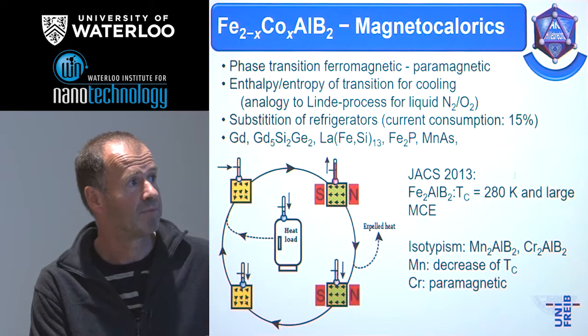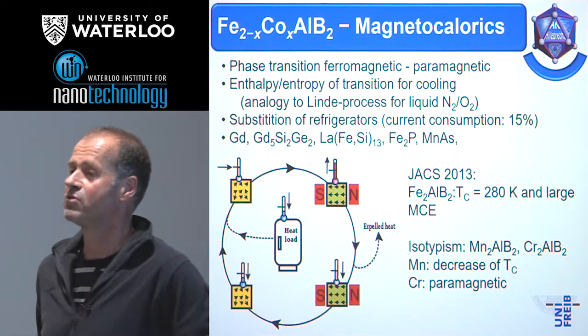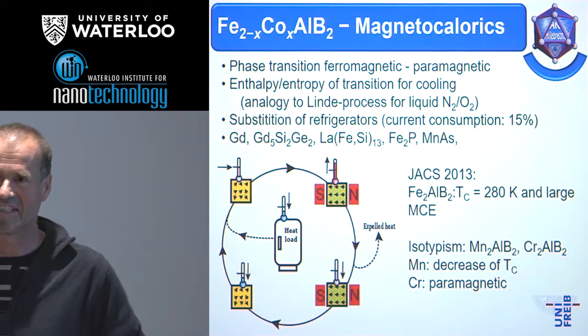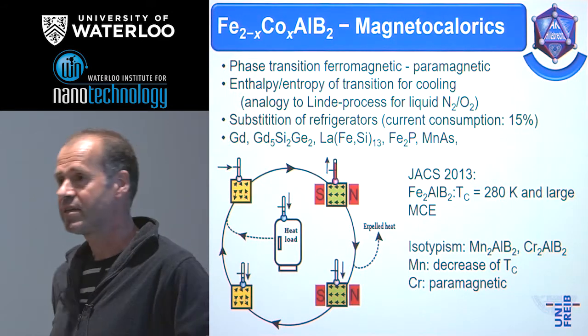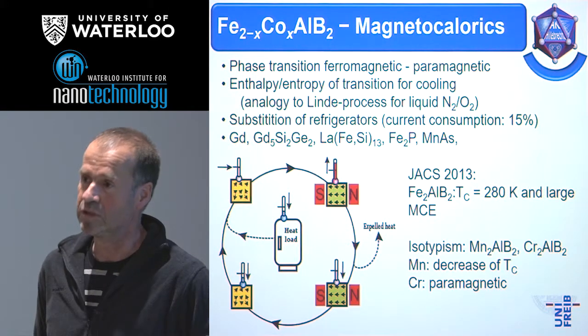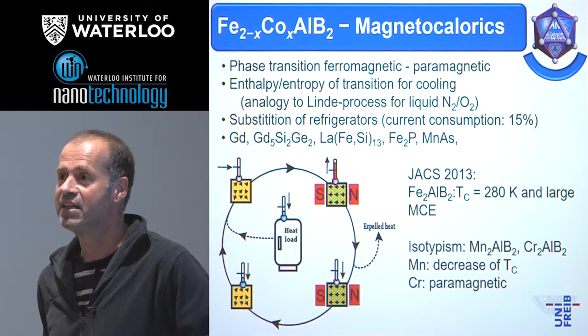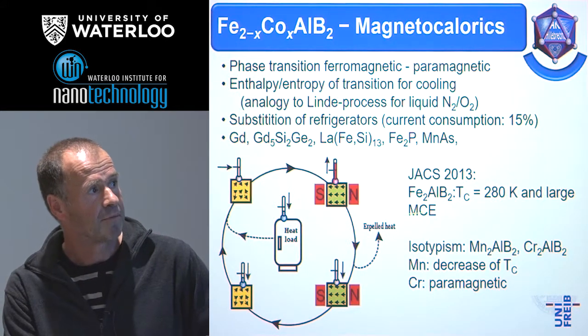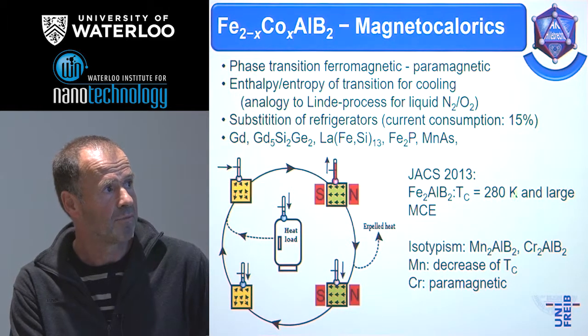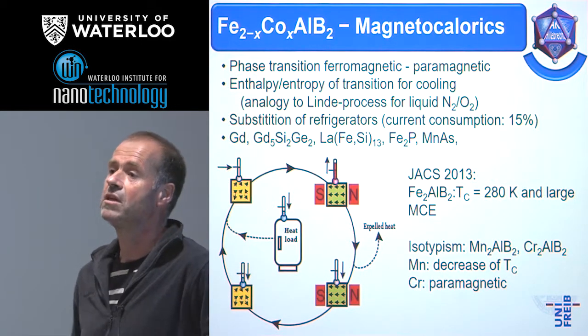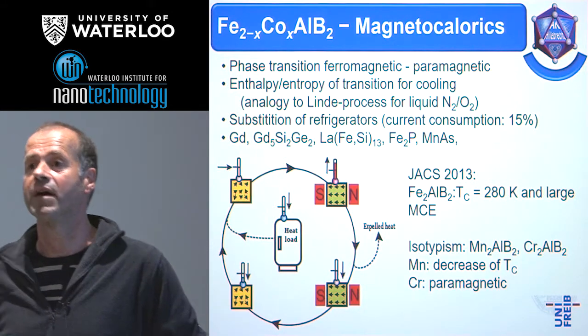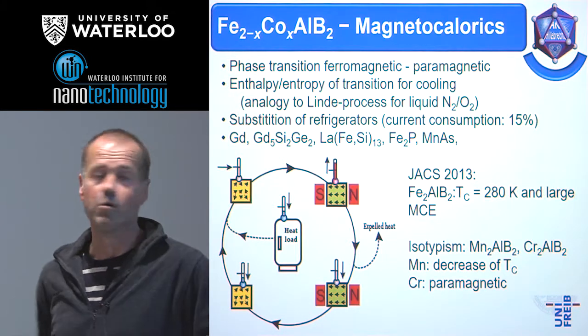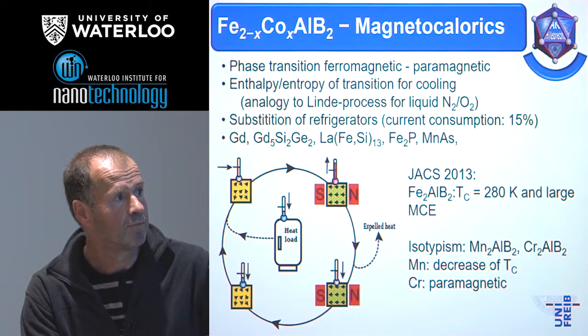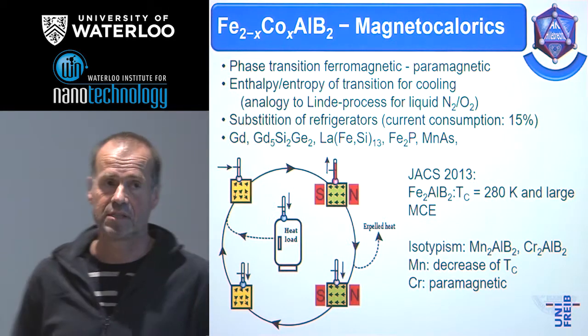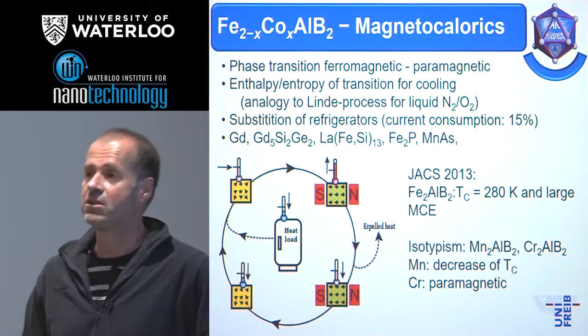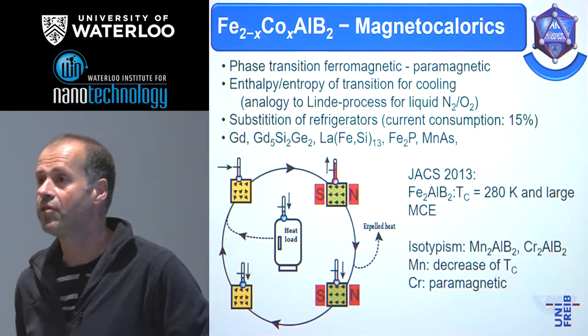Very recently there was a nice publication on a boride, and boron chemistry or borides is one of our centers of competence that we have in our group. And at that time I had a master student in the group of Yuri, and he said to me, oh look, there is a nice idea in what they have published, because this compound has a Curie temperature around room temperature, and that means that you can use it for a magnetocaloric cooling device from room temperature to lower temperatures. And there we had lots of experience on these borides, and the idea is, can we do a substitution of the transition metal so that we can decrease the Curie temperature but maintain the good magnetic properties.